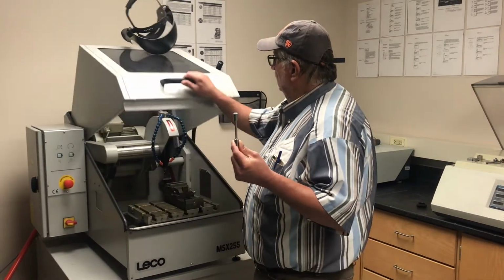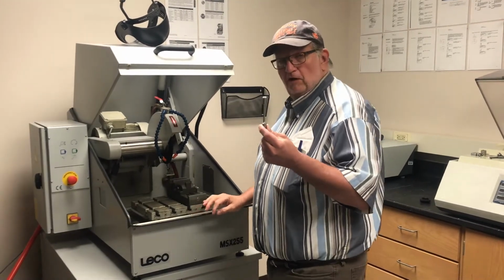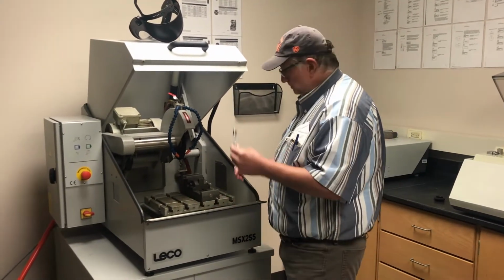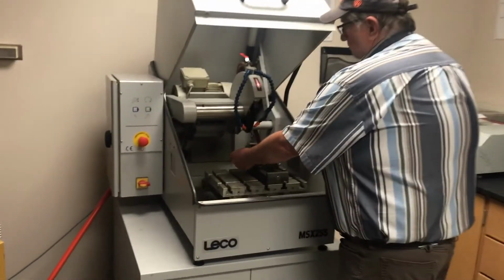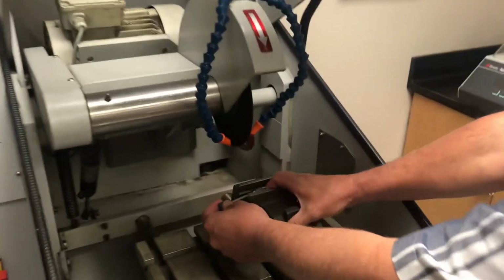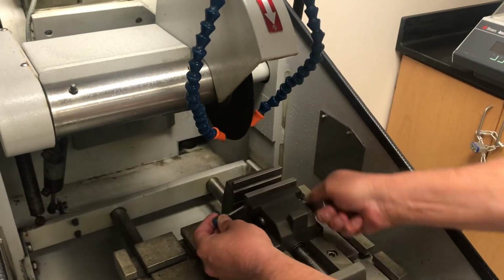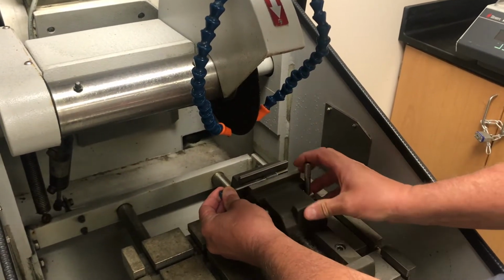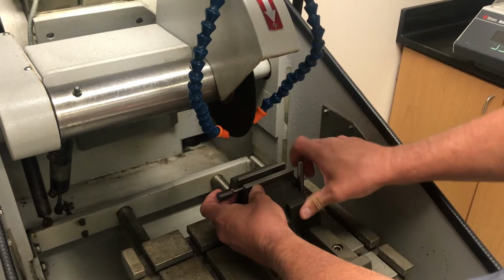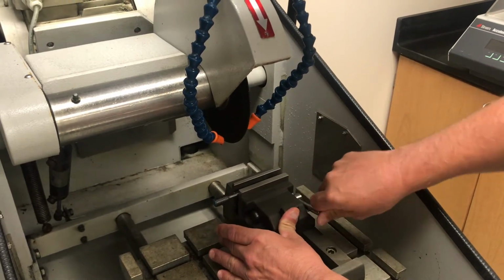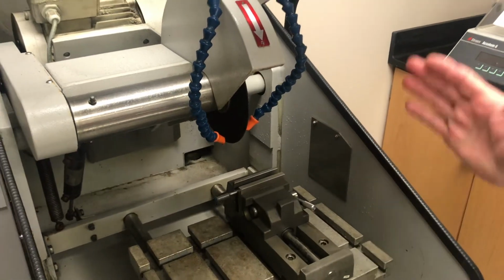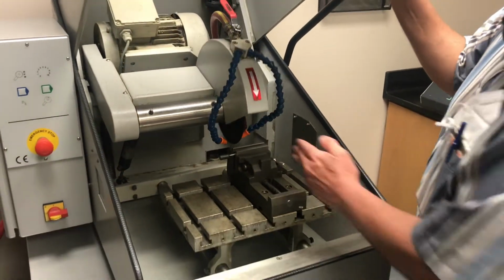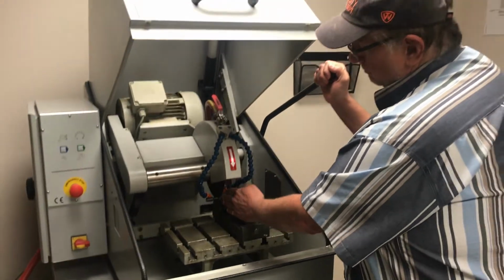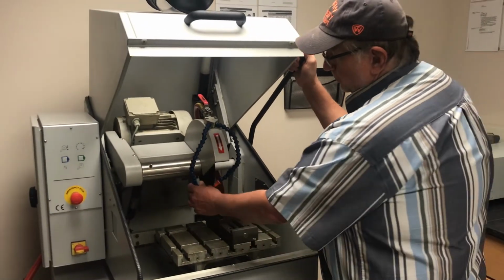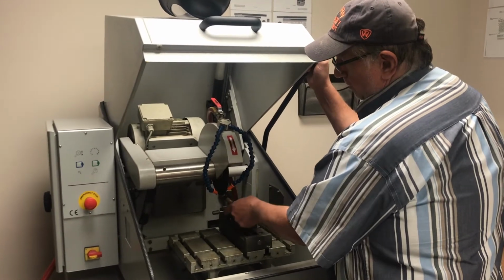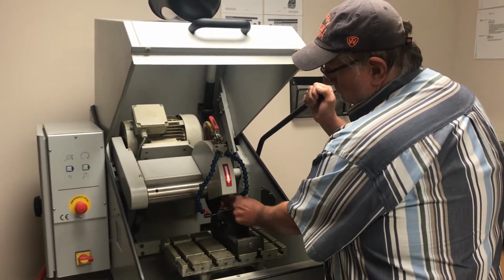So this is the Leco abrasive cutoff saw. Take your sample, place it in the vise, which is on a linear bearing. Place the sample in the vise, push it with your hand and clamp it. It's very secure. Now, notice that the blade is positioned just to the left of the vise, which is what you want. And you also want to make sure that the lubricant nozzles are pointed at the cutting action, okay?